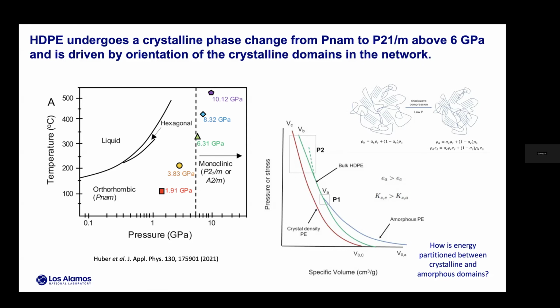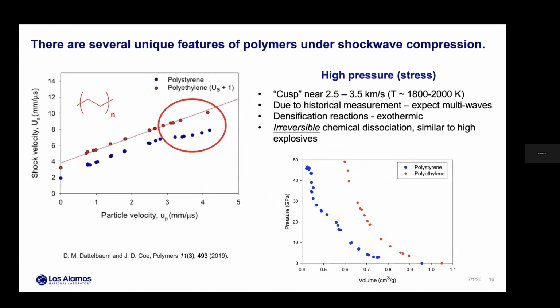And I'd say the next thing we need to do is do this as a function of strain rate. So we do have some of the data collected where we've done dynamic DAC experiments, and I'd like to tie all that data together as a function of strain rate. Okay, so now I'm going to focus on the high pressure regime and talk a little bit about dissociation.